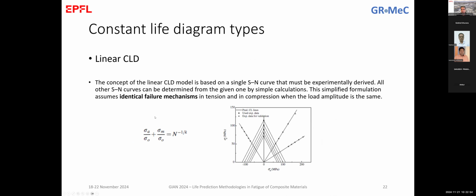So here you see typical CLDs, starting with the linear CLD. It's similar to the Goodman diagram. You remember the Goodman diagram was like that. This is the definition of the Goodman diagram, and all the lines start here from the UTS of the material. So the static tensile strength, and here it goes to the UCS, the ultimate compressive stress. And so this diagram, the linear, has been introduced 15 years ago, more or less, assuming that there are the same failure mechanisms between tension and compression, which of course you see is not the case in our material.